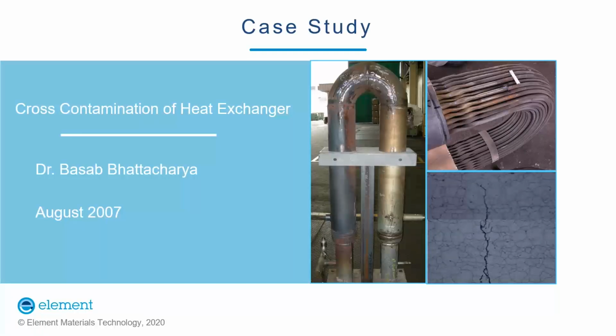Our client detected a leakage as well as flue gas cross-contamination in a U-shaped heat exchanger after little more than 3,500 hours of operation. The heat exchanger consisted of tubes and the shell which is covering these tubes. Material used for the shell was 304 stainless steel and the Incoloy 800H was used for the tube. As per client supplied information, the temperature of the superheated steam at the inlet, which is also called the hot side, was supposed to be 500 degrees Celsius.